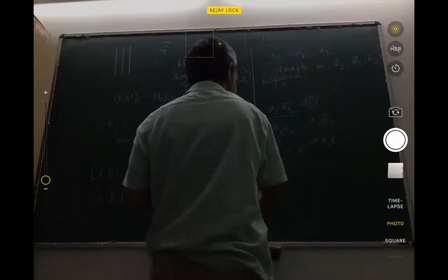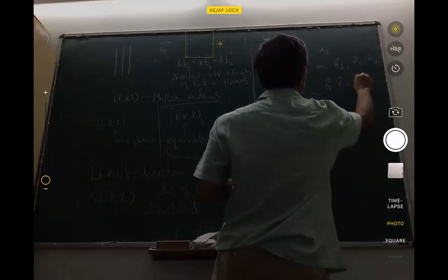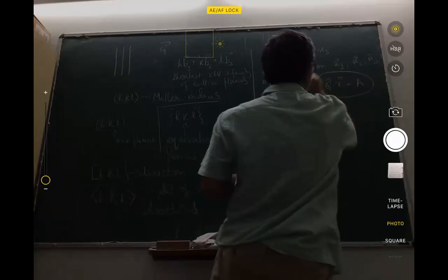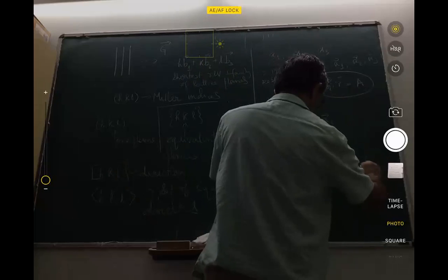What I want to write is, let us say, G dot R is equal to a constant on the planes, saying the same thing. So then what I have here is 2 pi x1 times h is equal to a constant, and so x1 is equal to that constant over h. Or conversely, h is proportional to 1 over x1.